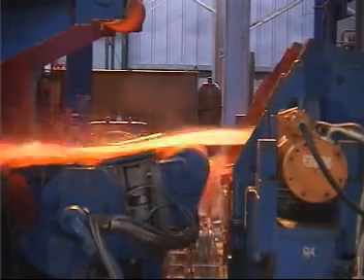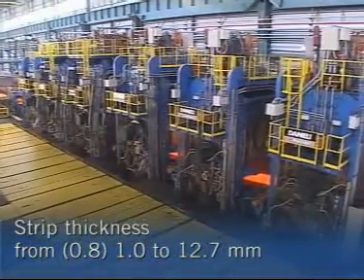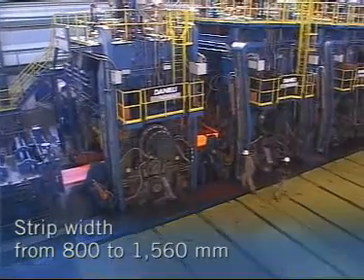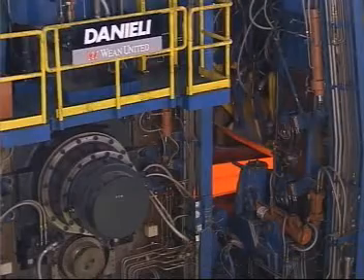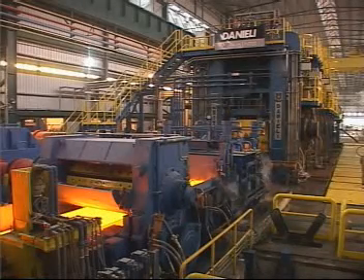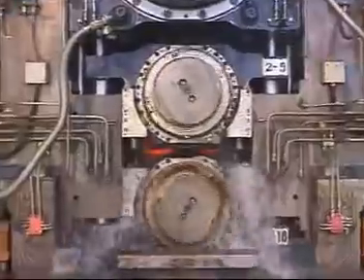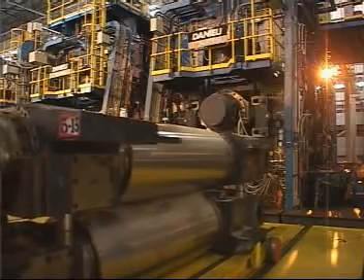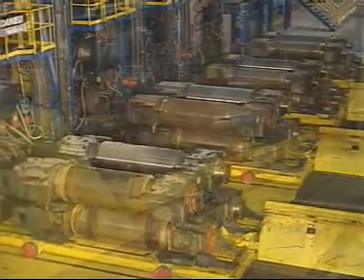The production of ultra-thin strips down to 0.8 millimeters is possible thanks to the Danieli patented F-squared CR flexible crown and free rolling stands on F2 and F3. This concept embodies powerful, effective, and reliable solutions to shift and cross the rolls under the rolling load to improve the strip crown and flatness control range in conventional or semi-endless rolling mode. A quick changing system enables the complete work roll change for the finishing mill in less than 8 minutes.